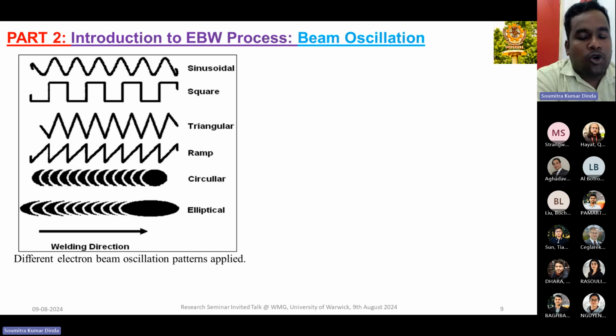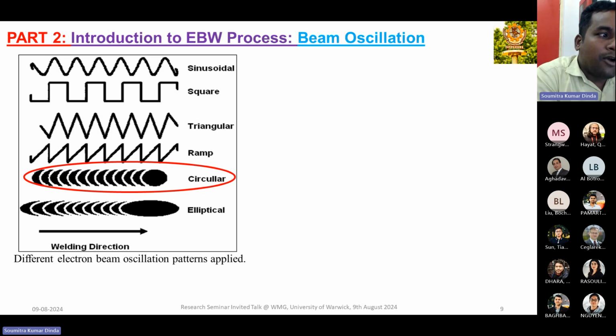Now, with the conventional welding process conditions, suppose voltage, current, welding speed, we add one more welding condition, that is the beam oscillation. And beam oscillation is the deflection of the electron beam from the straight line path to give any periodic motion. And there are different possible oscillating patterns, say sinusoidal, square, triangular, ramp, circular, elliptical. But the literature suggests that there is a negligible effect of different types of pattern. So we choose the simplest one, that is a circular oscillating pattern, in our case study.